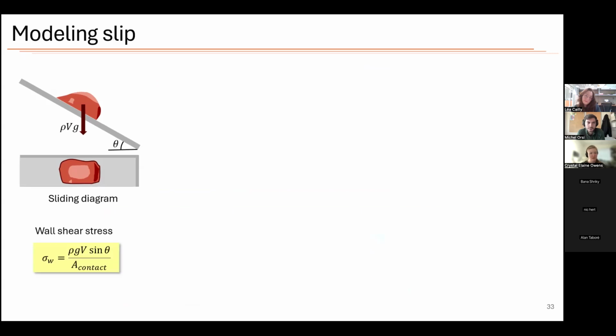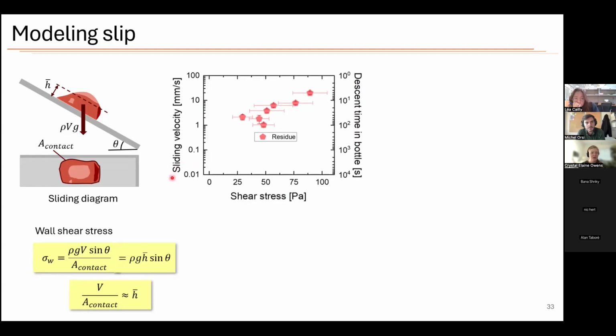The equations that we're working with here: we have a wall shear stress, which is the force of gravity divided by the area of contact. The top image here is a side view, the bottom image is a top view. Then we can approximate V over the area of contact as something like an effective height and use that to develop an equation. So rho g h sine theta describes the approximate wall shear stress as the ketchup falls. We measured the sliding velocity using videos and my apparatus. I have the sliding velocity, and then I have the time for the ketchup to fall, knowing that the bottle is 100 millimeters tall for the bottle that I have.